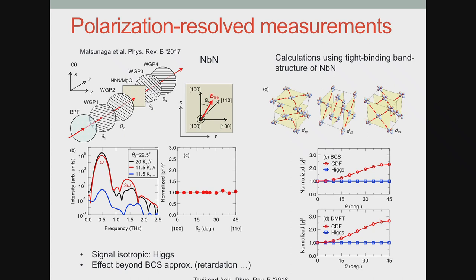And this is the puzzle, because it's very hard for any generic system to have the pair-breaking contribution be so independent of polarization orientation. Only the Higgs mode actually guarantees you that. So this is the puzzle. In the BCS approximation, you would expect the Higgs contribution to be orders of magnitude weaker, but yet in the experiment it seemed to be the relevant one for these measurements. So I think there is still no good explanation for what reason the Higgs mode apparently seemed to dominate these measurements.